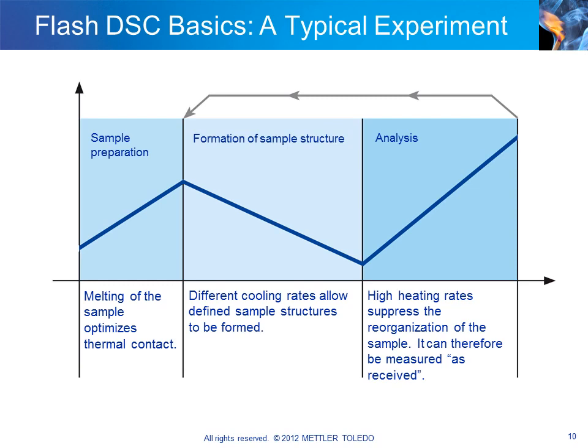The schematic diagram shows a typical Flash DSC temperature program. In the first heating segment, the sample is usually melted in order to optimize thermal contact with the sensor. In the second, controlled cooling segment, defined structure can be produced. In the third, heating segment, the sample is measured until it finally melts.